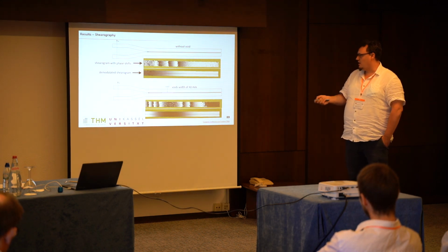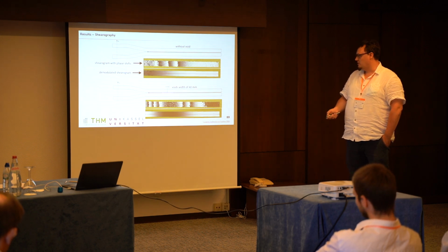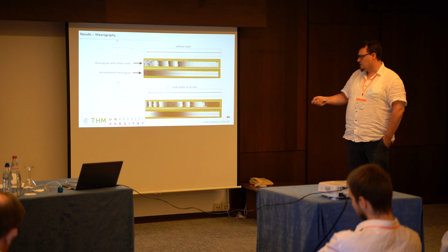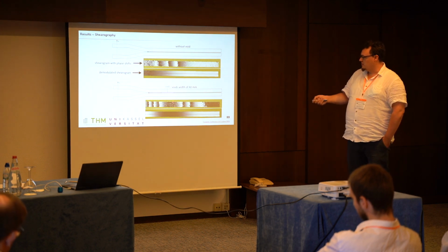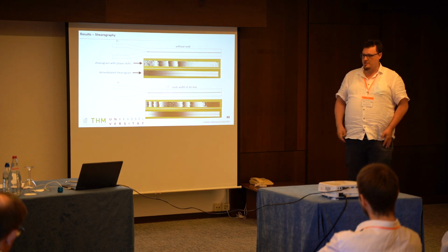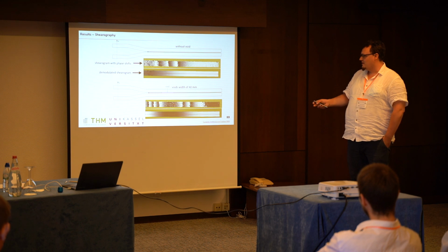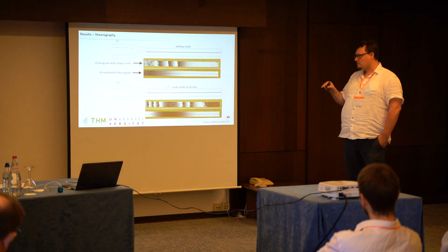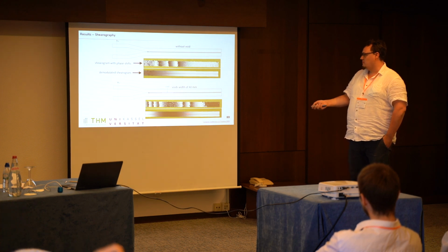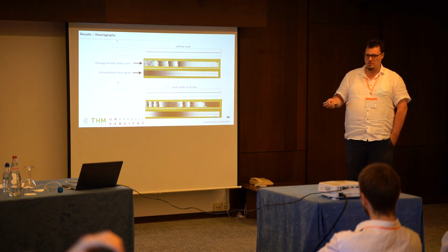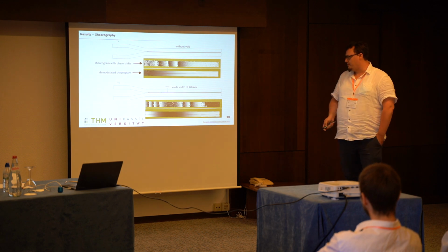Now the interesting part, the specimen with voids of 40 millimeters. The shearogram looks slightly different, and in the middle where the void is, you can see there's something unexpected. That's the void, and the progression of this is not matching very well with our expectation from the deflection.